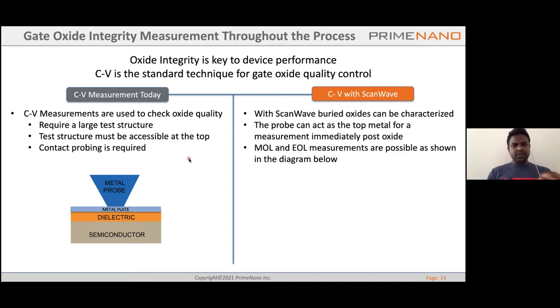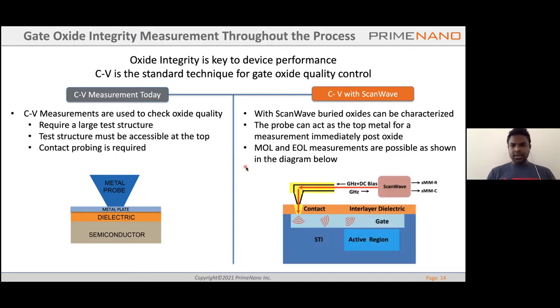With microwaves, I want to show you a very cool thing: when the microwave probe contacts the metal electrode, it makes the metal electrode a proxy for the microwaves, and you can pass the microwaves from this metal to the contact via, and actually probe the device which is buried deeper, and you can access the characteristic response or the capacitance voltage response of this device.